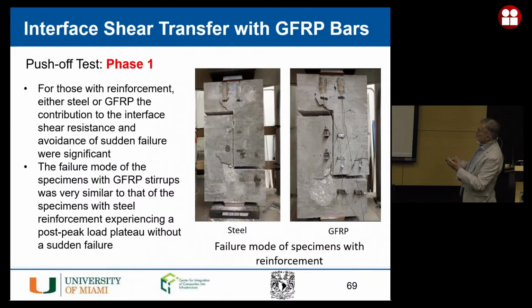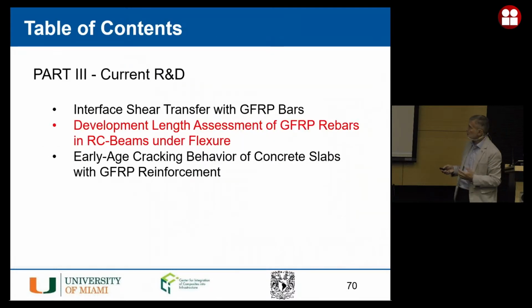So these are the results of phase 1, and basically in words is what I told you. And then look at the pictures. We stop the test after a while, after you have all that deformation. But look at the steel specimen, the FRP specimen. If I delete the caption, would you know which one is which? They are identical, okay? And so you see that gap that was there to begin with obviously has become much smaller. The crack has opened up, but you don't see anything much different.